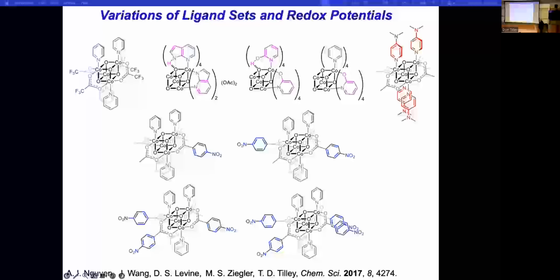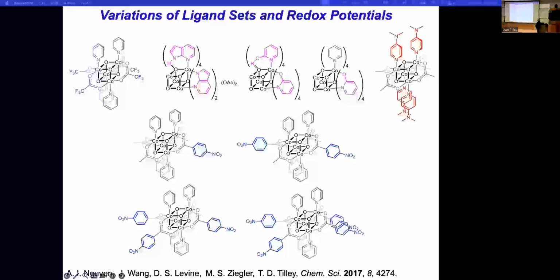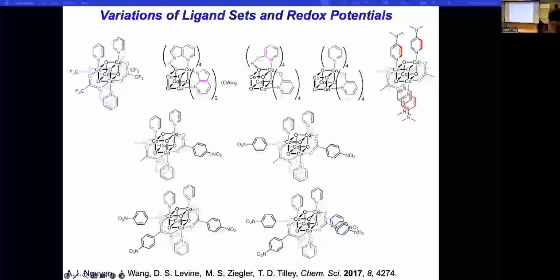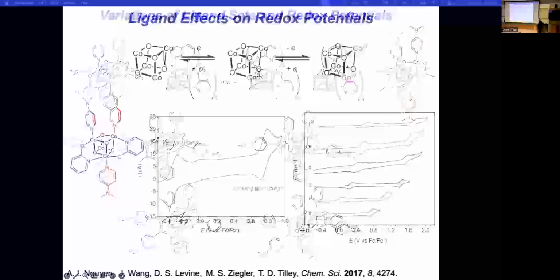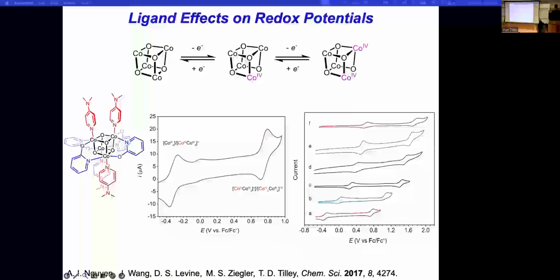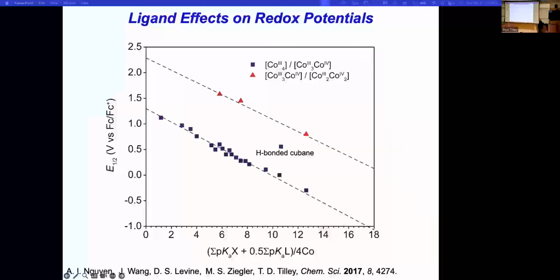So Andy found that he could very easily substitute ligands in the cubane and put in more electron withdrawing groups, more electron donating groups, put in hydrogen bonds, do a lot of different things. And that allowed us to start interrogating the redox properties for not only the first oxidation event, but the second one. So you can actually see the second oxidation in many of these cases. You see a lot of that data laid out here. So the species on the left is one of the more electron-rich ones that we have.